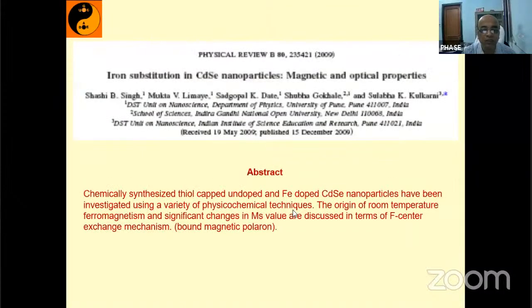This is one of the examples that the Pune University people have done. Basically, for example, if you go with nanoparticle samples, with in-laboratory spectra you will not get very good quality spectra there. But if you go with synchrotron radiation photoemission, then you can get very good quality. Here, basically, the nanoparticles are cadmium selenide with iron substitution. And normally in the laboratory, because the nanoparticle size itself is very small, the iron doping, whatever substitution is there, will not give the signal.